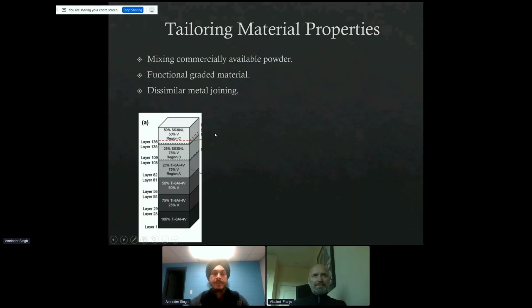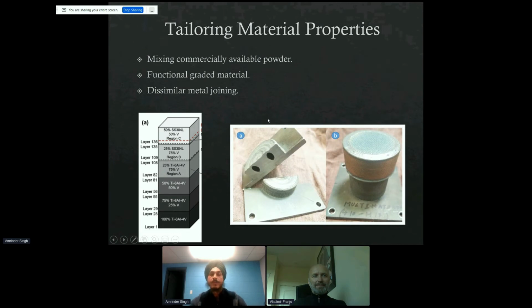Why is this technology so important? Because we can tailor the material properties. If we need a hard material on a soft one, yes, we can do it. If you need a functionally graded material, we can do it too. We can have different compositions of different powders in every layer to make a functionally graded material. For example, if you have a material which is softer on the top and hard on the bottom, we can go gradiently harder, not just from soft to hard, to retain the properties.